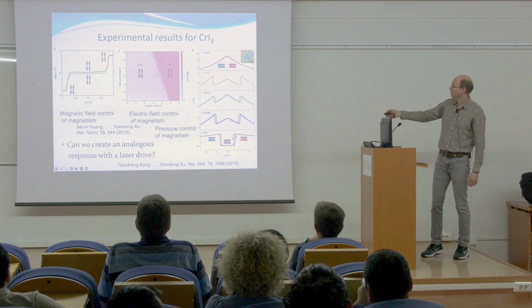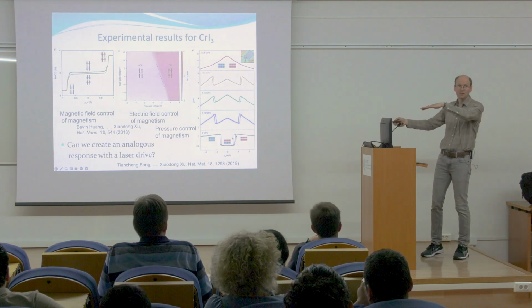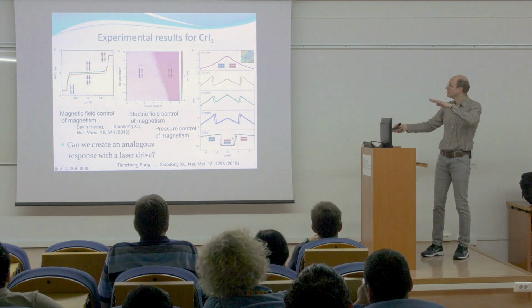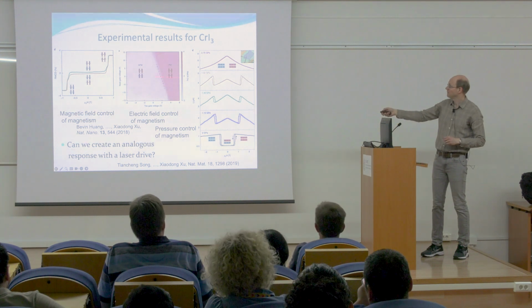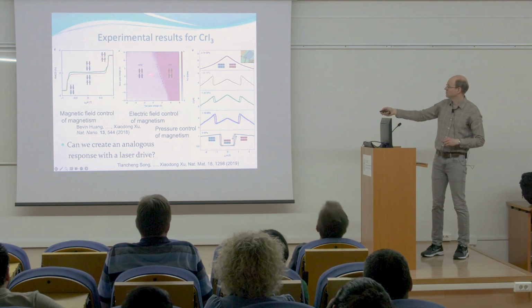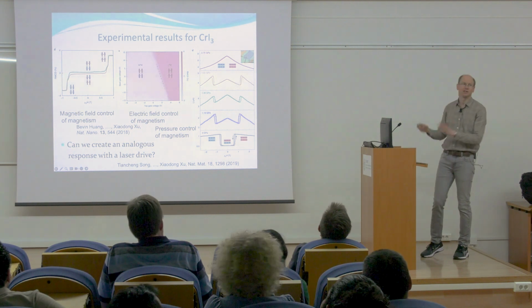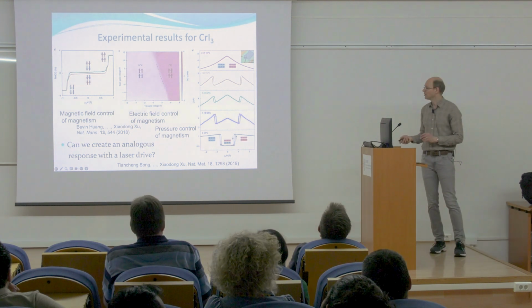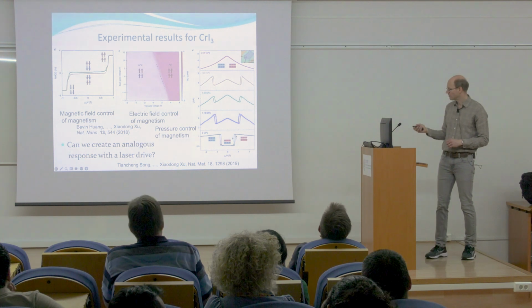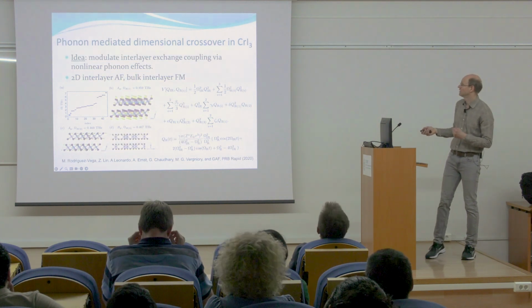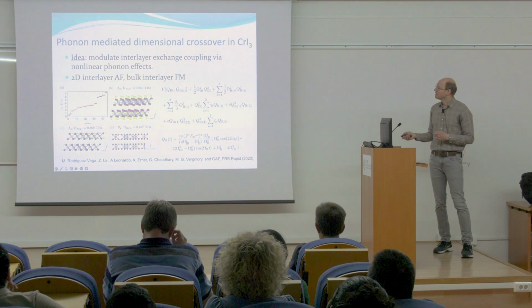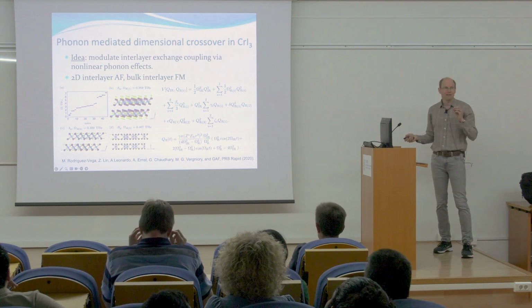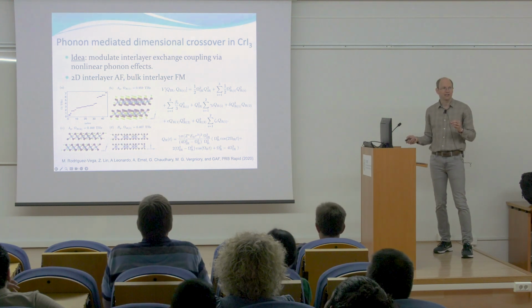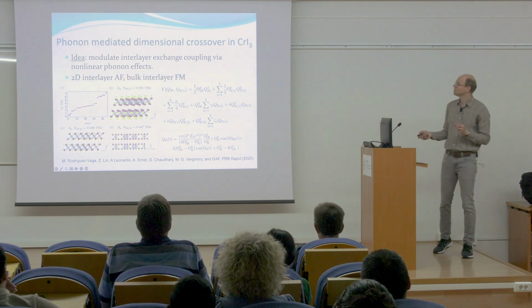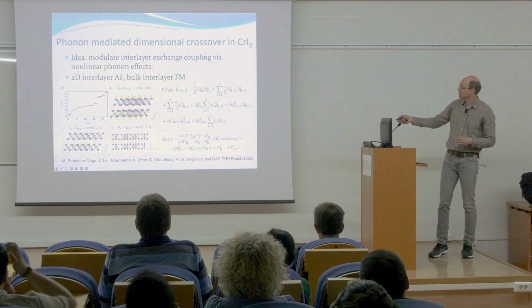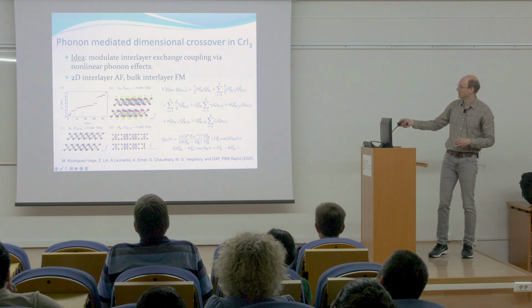If you put the system under an electrical gate, apply a voltage, then you can also change the magnetic orientation between the layers. And if you put it under great pressure, then you can change it as well. So the question that we investigated here is whether we can do the same sort of thing with light. We wanted to ask whether we can create this transient distortion in the lattice via the nonlinear phononics regime that would change the exchange coupling between the layers in the bilayer system.